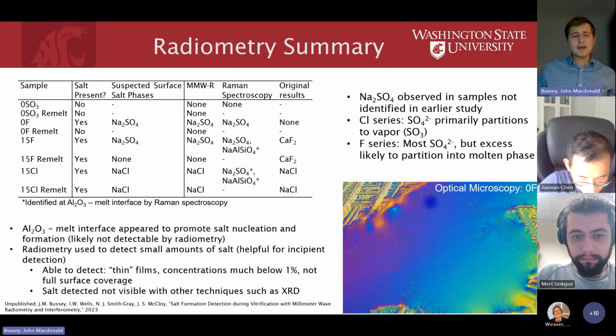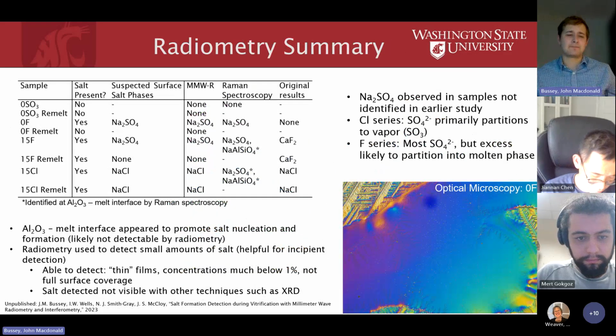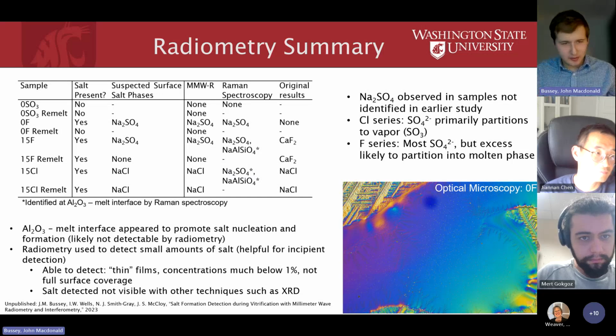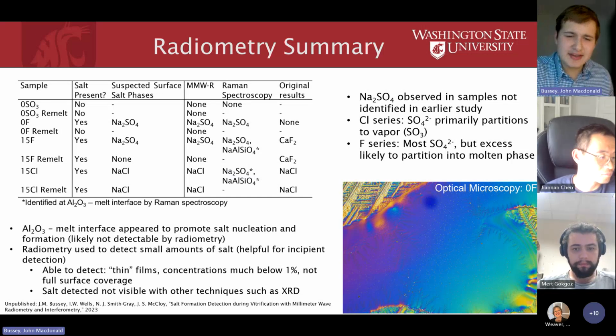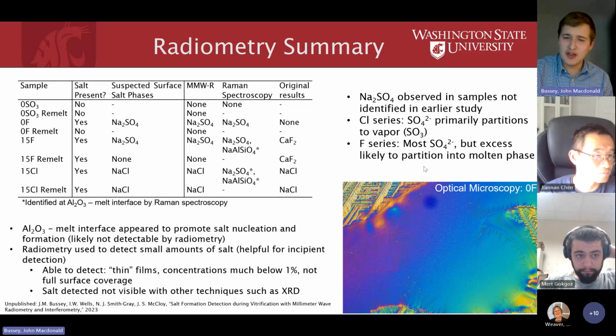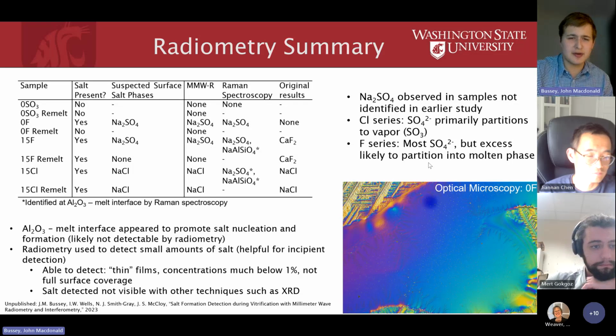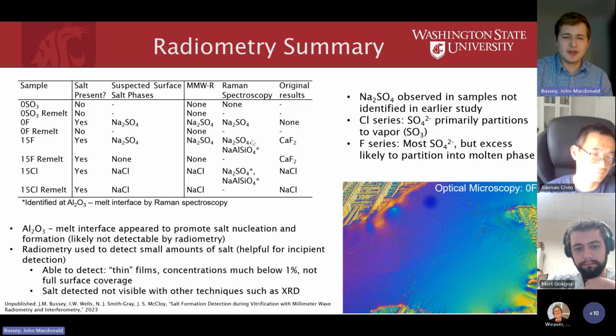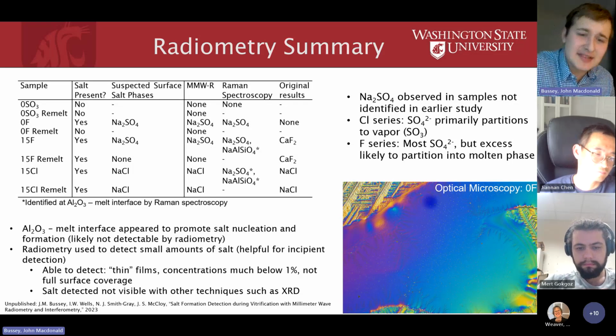So I mentioned most of this, but again, we were able to see this with the millimeter wave, including some things that we weren't able to see with other methods, particularly with X-ray diffraction, but also even though the Raman spectroscopy didn't necessarily immediately pick up some of the things that we observed.